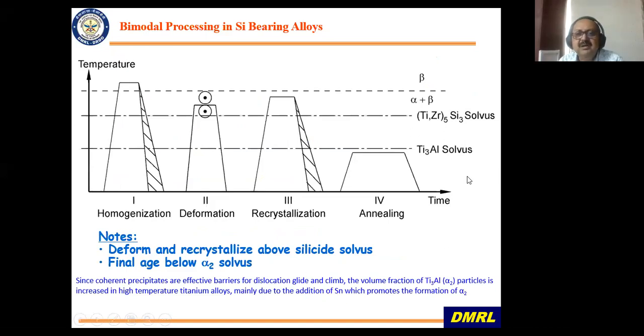Now, this is how the near alpha titanium alloys are processed. Again, homogenized, similar. Here you can see, other than the alpha plus beta regime, there are also two other solvuses which have come in. That is the Ti silicide solvus, which is higher, and the Ti3Al solvus. So you have to be careful while processing these alloys. You carry out deformation and also recrystallization above the Ti silicide solvus, because once silicide precipitates,